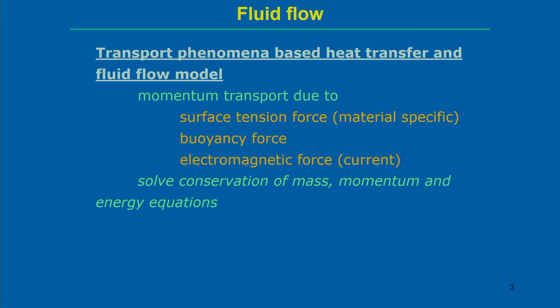Starting with fluid flow — or transport phenomena based heat transfer and fluid flow analysis — while talking about fluid flow analysis, we are not only considering fluid flow but also the material flow and thermal analysis, because temperature distribution is equally important. In general, a transport phenomena based heat transfer and fluid flow model in welding processes involves energy transfer from the arc, which induces driving forces so that momentum transport occurs. This momentum transport happens within the small weld pool because of surface tension force, which is material-specific and changes in the presence of surface active elements.